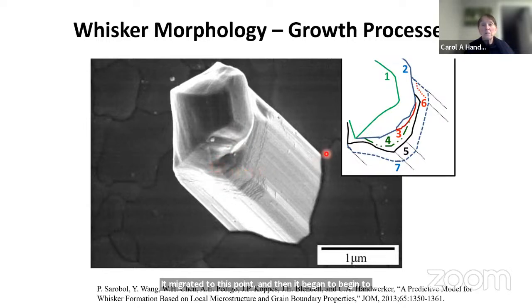And then at some point, at about position number 5, the whisker uniformly grows from the film. What that means is all of the grain boundaries present in here, all the underlying grain boundaries, are accreting atoms. The atoms are diffusing there, and then they're pushing up the whisker uniformly. So you can see what the underlying grain boundaries are. These are grain boundary grooves here. So this is the whisker. This defines where the grain boundaries are in the film for the whisker grain. And here, these are the grain boundaries of the film, the grains that are surrounding it. So this, again, is a shallow grain, and we'll get to some of those features in a minute.